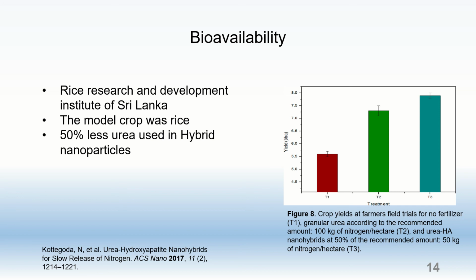nanoparticles. Figure 8 here to the right compares the yield per hectare of rice with no fertilizer, which is T1, the recommended amount of granular urea, which is 100 kilograms of nitrogen per hectare, which is here in T2, and the urea-hydroxyapatite nanohybrids at 50% the recommended amount of nitrogen, or 50 kilograms per hectare, which is here in T3. What the data shows is that the nanohybrids actually outperform the pure urea, even at half the amount of urea.